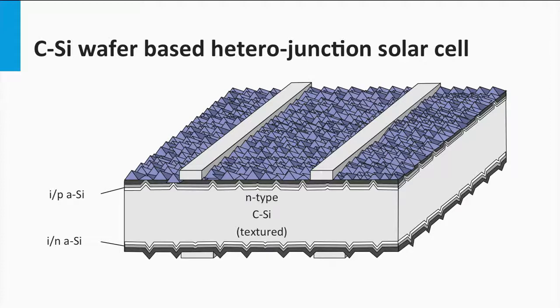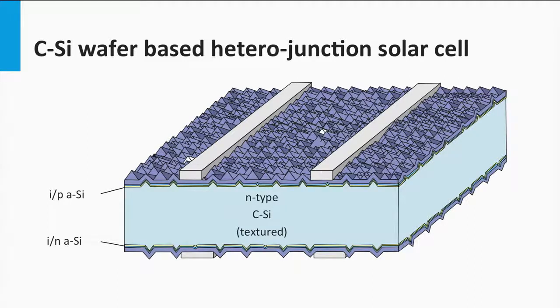The ITO is needed as the conductivity of the p-type layer is too poor. This results in such small diffusion lengths that a practical metal finger spacing cannot be achieved using the p-type layers. Therefore, ITO is used. An advantage of the HIT cell concept is that it allows to introduce the same contact scheme at the n-type backside. It means that this solar cell can be used in a bifacial configuration. It can collect light from the front and scattered and diffuse light falling on the backside of the solar cell.